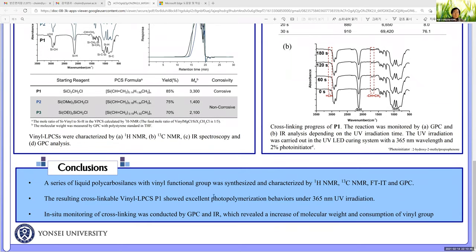In conclusion, we prepared a series of liquid polycarbosilanes with the vinyl functional group. This compound has been characterized by proton NMR, carbon-13 NMR, FTIR and gel permeation chromatography. The resulting cross-linkable vinyl liquid polycarbosilane shows excellent photopolymerization behavior under 365 nanometer UV radiation. The cross-linking was monitored by the IR, which revealed an increase of molecular weight and the consumption of vinyl group, which depends on the irradiation time.